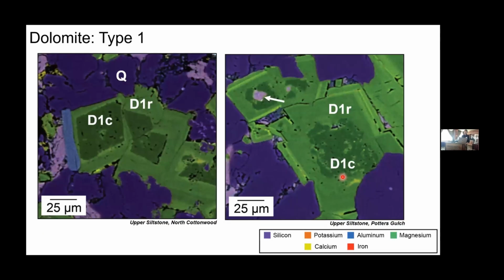So moving on to dolomite, and again, these are the phases that comprise a majority of the rock volume. And to remind you, we've broken dolomite into two phases. The first we're looking at here are these euhedral zoned dolomites. In the EDS, the darker color here represents a higher abundance of magnesium, and these progressively lighter phases represent an increase in calcium and iron as you move away from the center of these crystals.